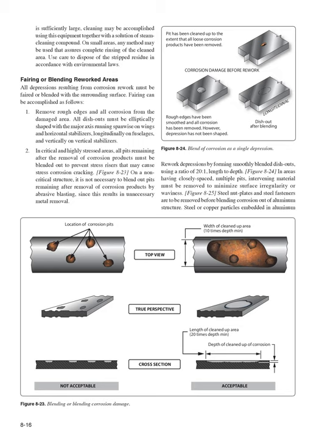2. In critical and highly stressed areas, all pits remaining after the removal of corrosion products must be blended out to prevent stress risers that may cause stress corrosion cracking. Figure 8-23. On a non-critical structure, it is not necessary to blend out pits remaining after removal of corrosion products by abrasive blasting, since this results in unnecessary metal removal. Rework depressions by forming smoothly blended dishouts, using a ratio of 20:1, length to depth.